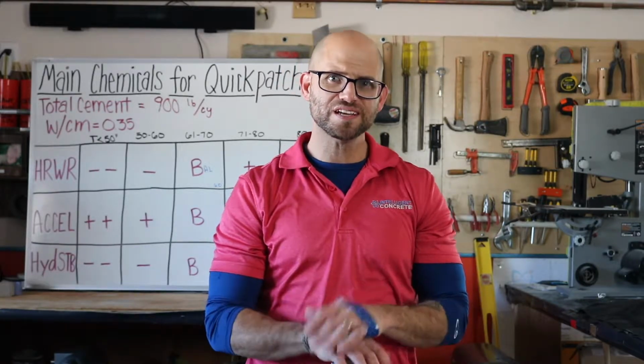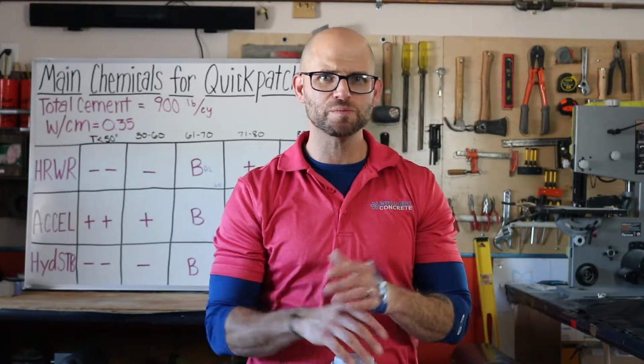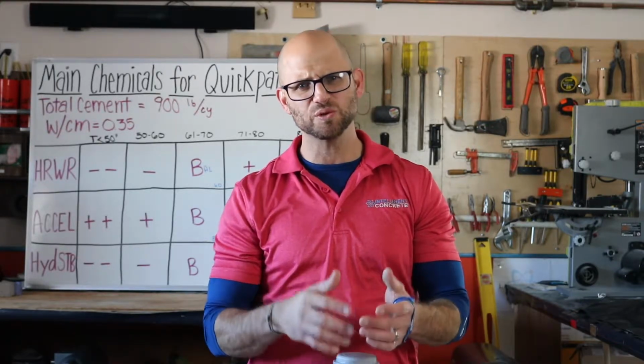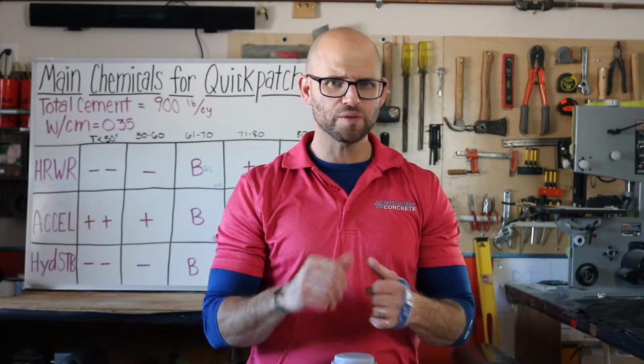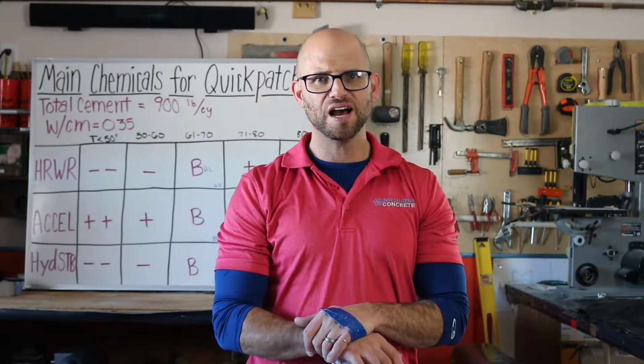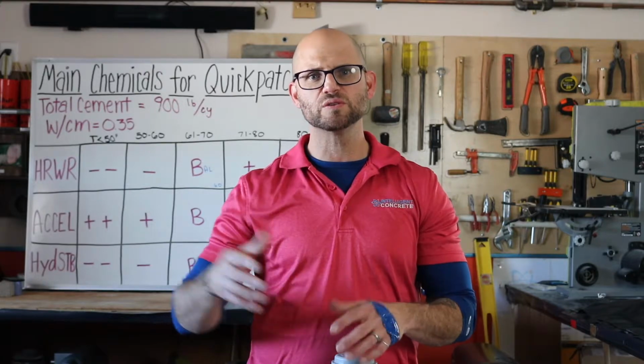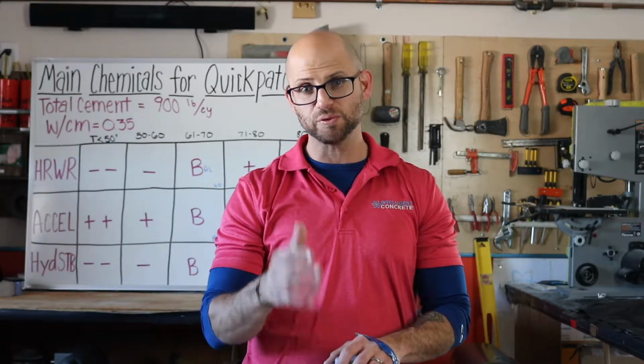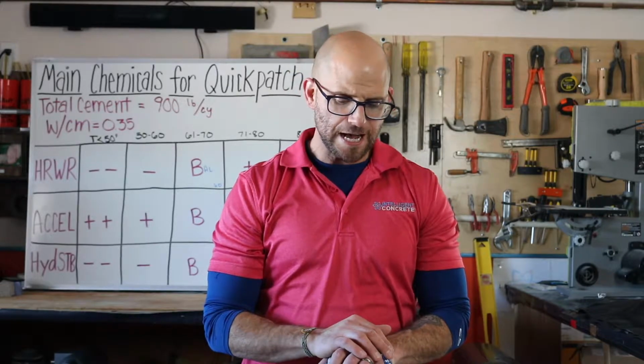Now the problem with accelerators is that normally you had to put them on the job site and they were pretty fast to act. So calcium chloride accelerators thrown in the back of the truck as a flake, and you would have a very short window to get that concrete down the chute into the form, placed, finished, and closed up.